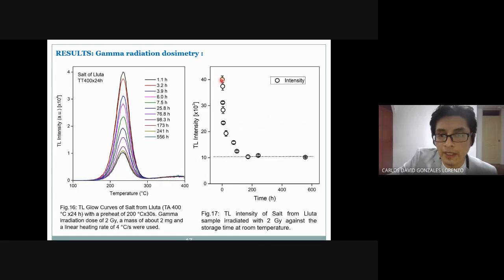So the fading shown for this sample with this previous thermal treatment is high. It decays about 75% in the first 173 hours, which is about 7 days. After that, no significant change was observed in the TL intensity up to 600 hours.